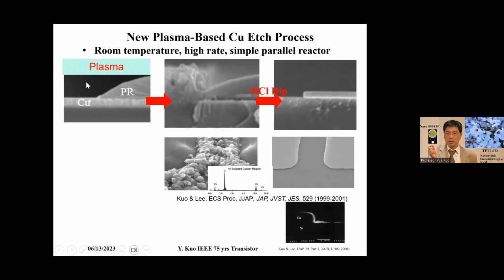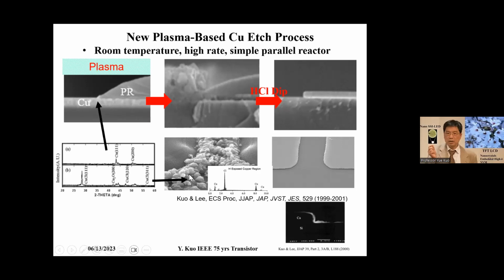And what we showed is, just like aluminum, copper is photoresist patterned, then exposed to plasma of chlorine or bromine. The copper will react with chlorine to form copper chlorides. Those chlorides are polycrystalline. And the conversion of copper in the exposed area is at high speed, for example, a few thousand angstrom per minute, even at room temperature. The whole layer is converted and stopped at the barrier layer. So selectivity is infinite to 1.